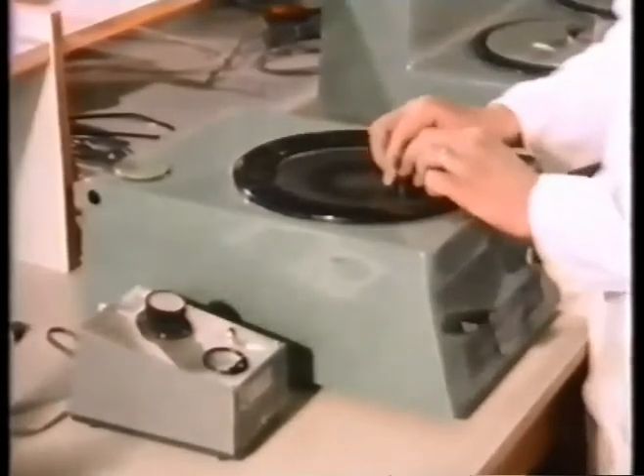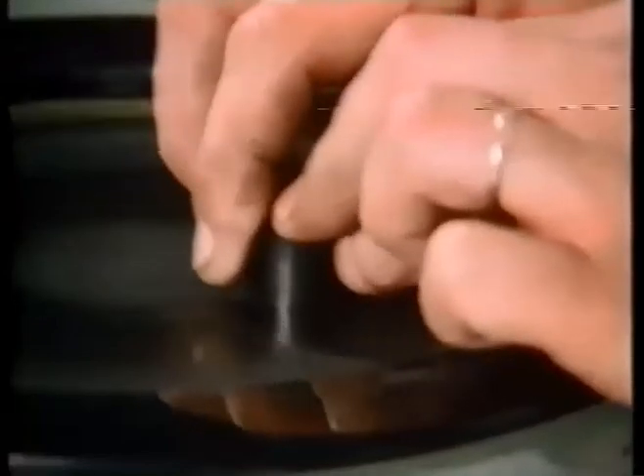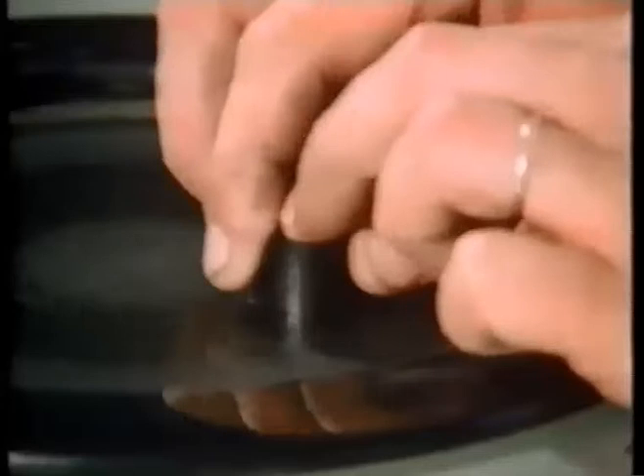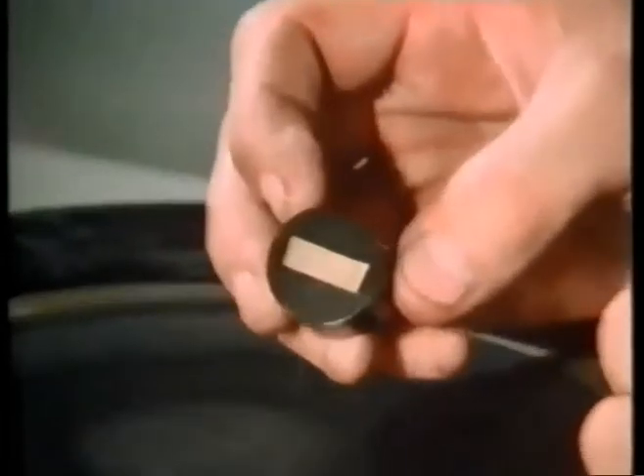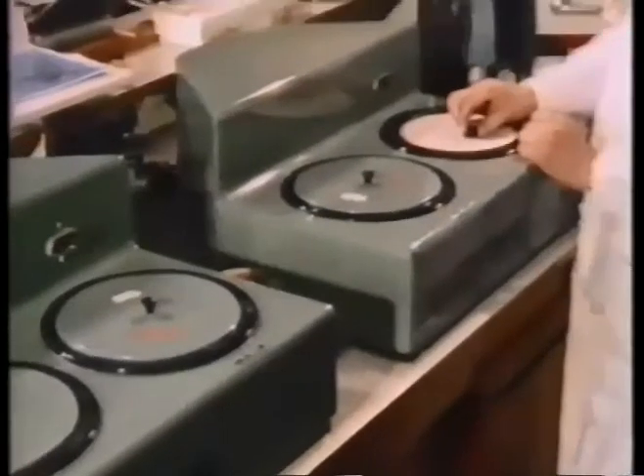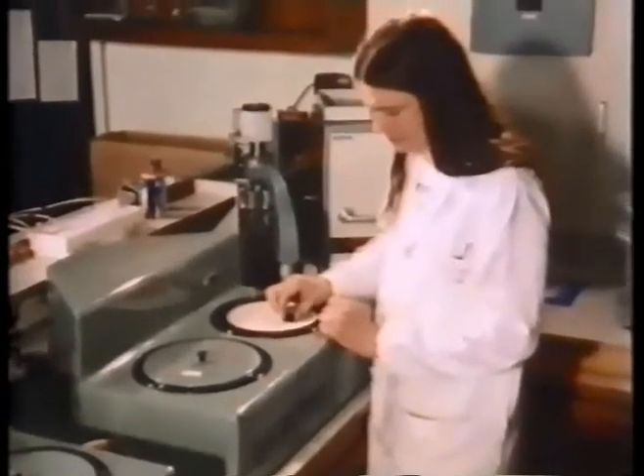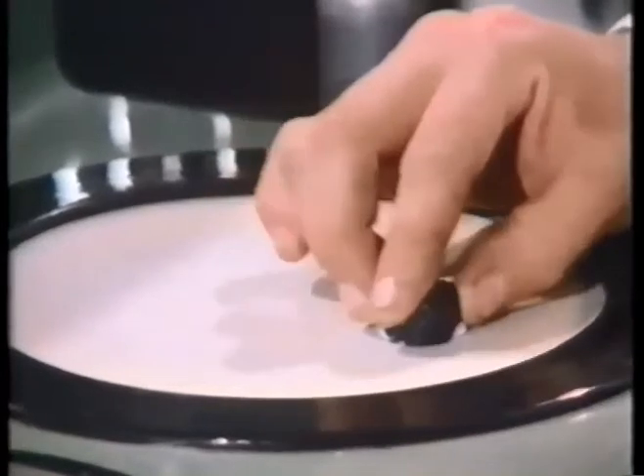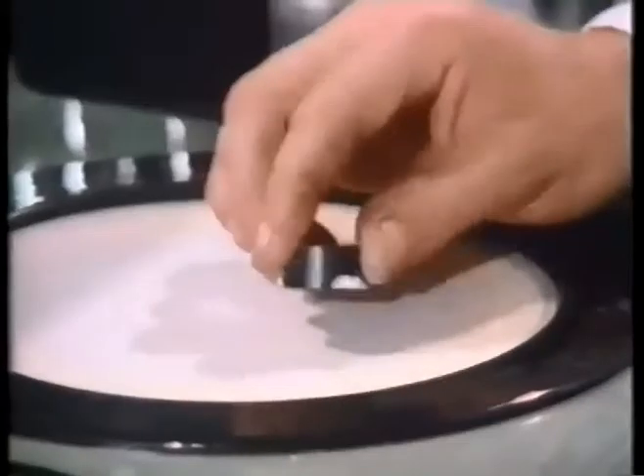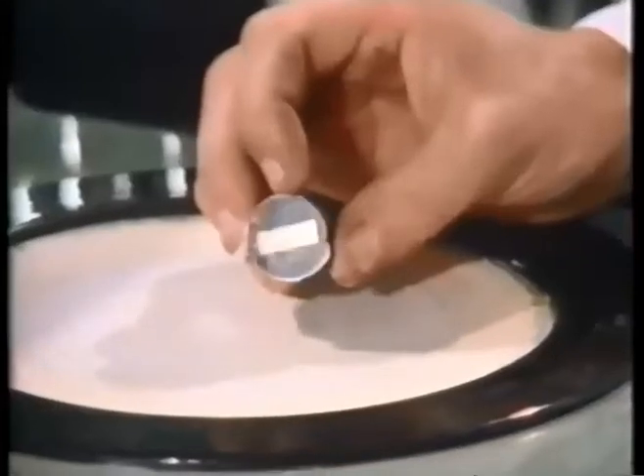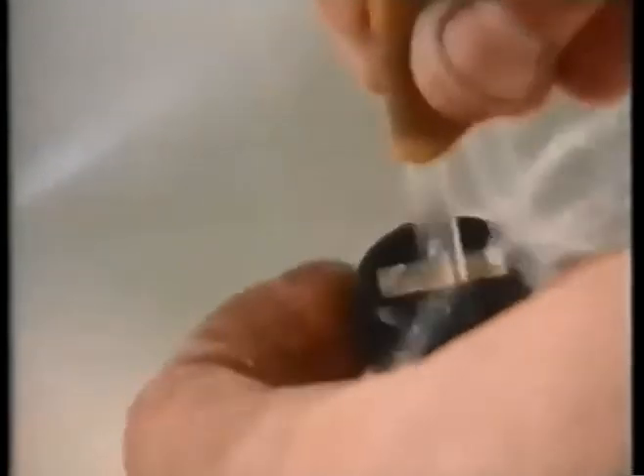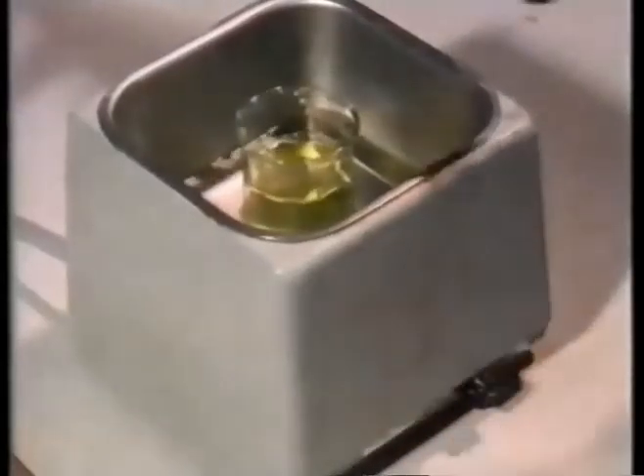The sample then goes through a polishing sequence on cloth wheels impregnated with diamond powder and lubricated with paraffin. During this, the specimen begins to take on a mirror finish. There's a series of wheels, each with a finer grade of diamond powder. And finally, the best finish is obtained by polishing on fine-grade alumina powder made as a slurry using water. The polishing debris is washed off using tap water, and the last remnants are removed by vibrating the sample in an ultrasonic cleaning bath.